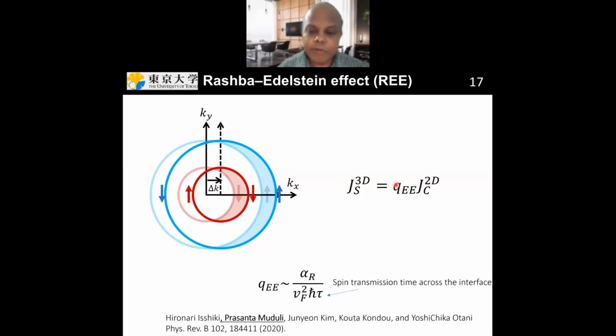And you can now define a quantity called Q, which you can define as the spin charge conversion efficiency. You can do a little bit of mathematics, and you can show that this Q is related to the Rashba parameter, the Fermi velocity, and the time constant, which is the spin transmission time across this interface. Now you can do a little bit of dimensional analysis over here. You can see that this is a 3D spin current, which has the dimension of ampere per meter square, and this is a 2D charge current, which has a dimension of ampere per meter. So Q has a dimension of 1/meter.